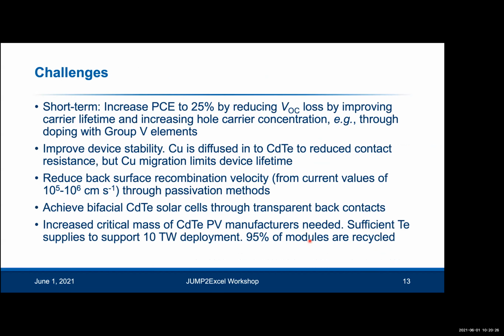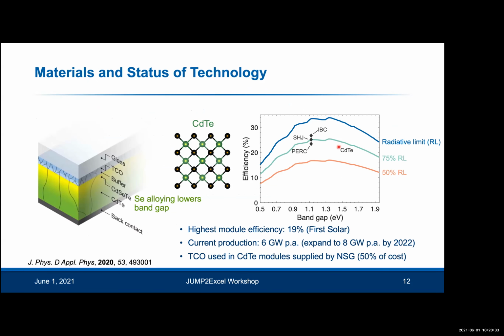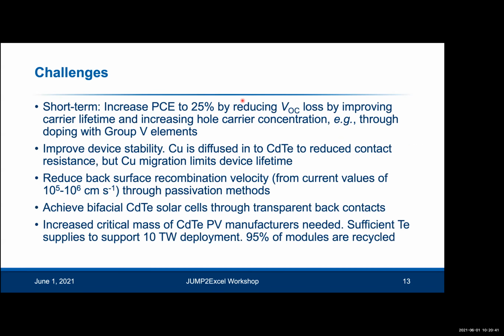So these are some of the challenges that people in the roadmap identified. One of the challenges is to increase the efficiencies to reach the 75% line. And you can see that corresponds to about 25% efficiency, which can be done by reducing losses in the open circuit voltage by improving carrier lifetimes.